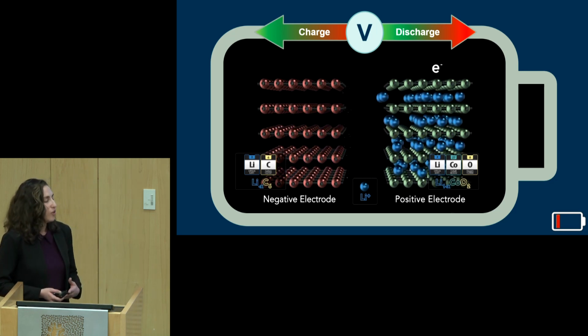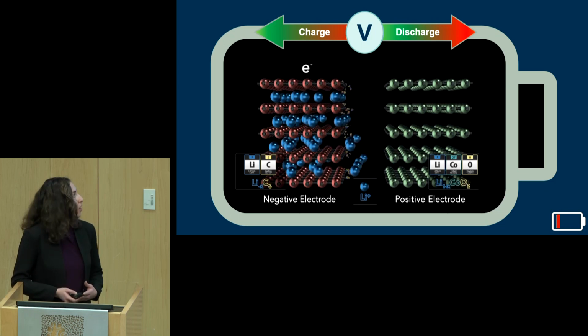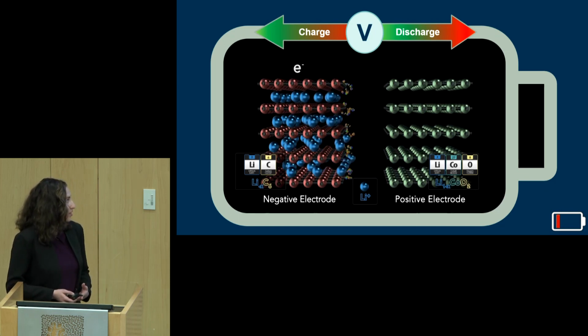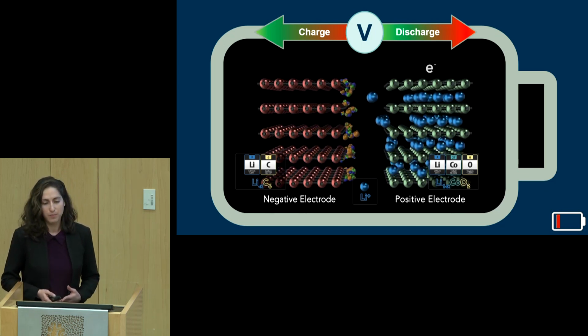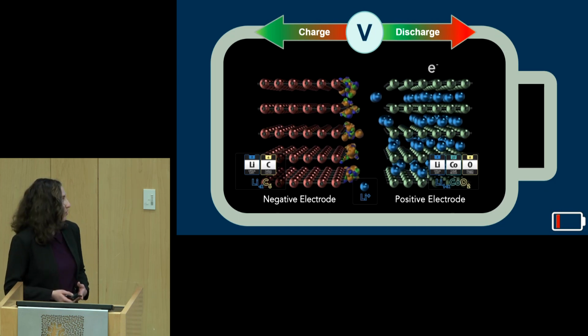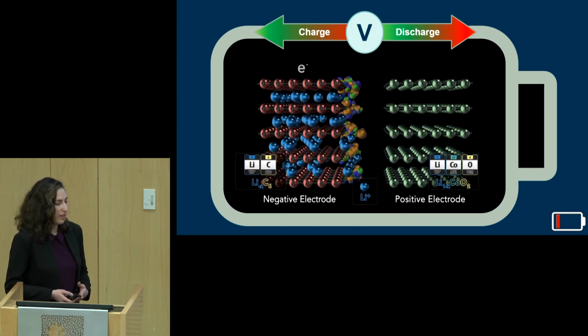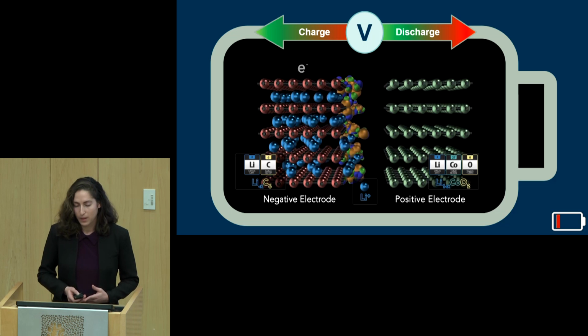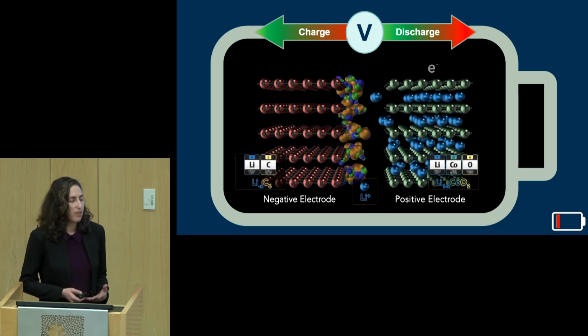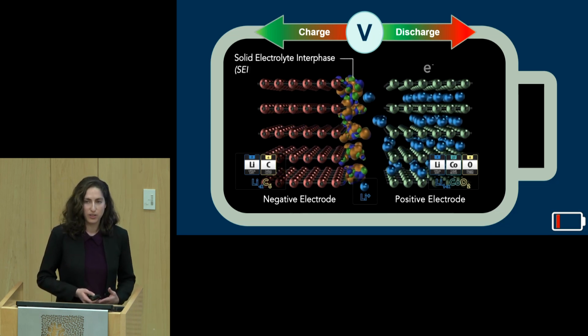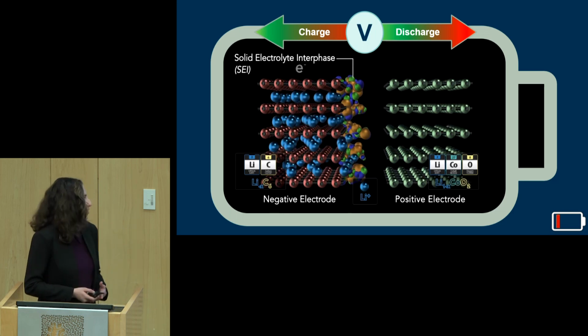But not only the lithium ions can react with the electrode. Also, the other electrolyte components can react, such as the solvent. These reactions form a surface layer called the solid electrolyte interface, or SEI. Ideally, this layer will not hinder the movement of the ions and allow them to enter the electrode, but this is not always the case.